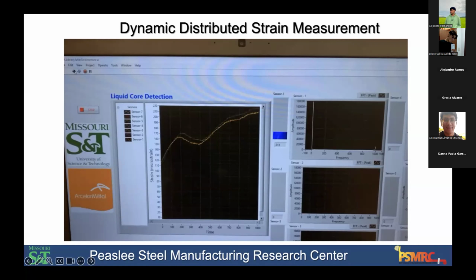And in fact, one of our application areas that's really interesting is that we've fiber optic instrumented injector panels. So one of the things we can do is monitor the temperature of the panel and tell, when we're injecting carbon and natural gas and oxygen, whether we're getting blowback or whether we're getting direct radiation exposure. So it tells us a lot about the dynamics of foaming in the furnace. It tells us a lot about scrap distribution and the potential for blowback and doing sidewall damage. And it's another really interesting application. That same application is also being used to detect water leaks in that environment too.